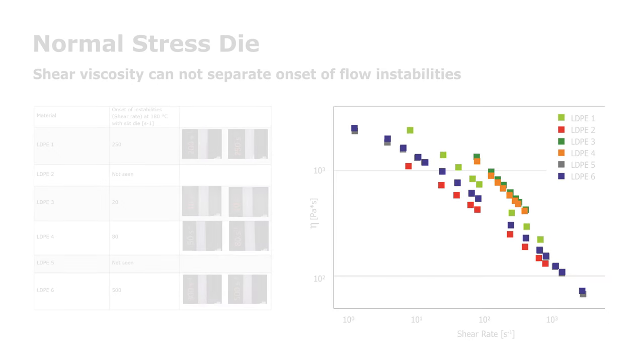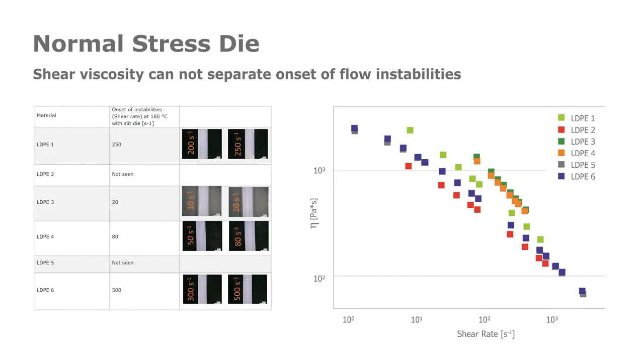The data we obtained now for six different LDPEs: LDPE 1 has an onset of sharkskin at a shear rate of 250. For LDPE 2 and 5, sharkskin is not to be seen. LDPE 3 has an early onset of flow instability, followed by LDPE 4, and LDPE 6 has a late onset at a shear rate of 500. Looking at shear viscosity, we cannot fully discriminate just using shear viscosity between the onset of flow instability.